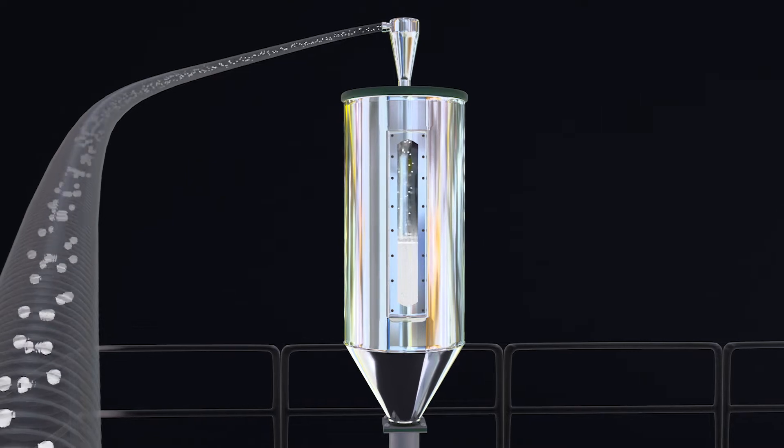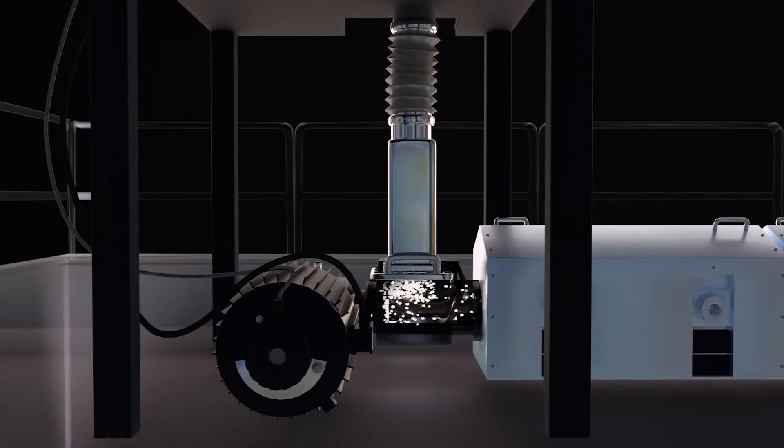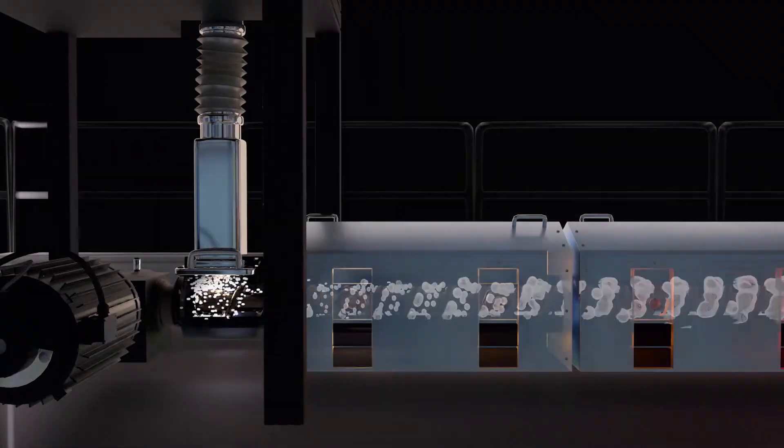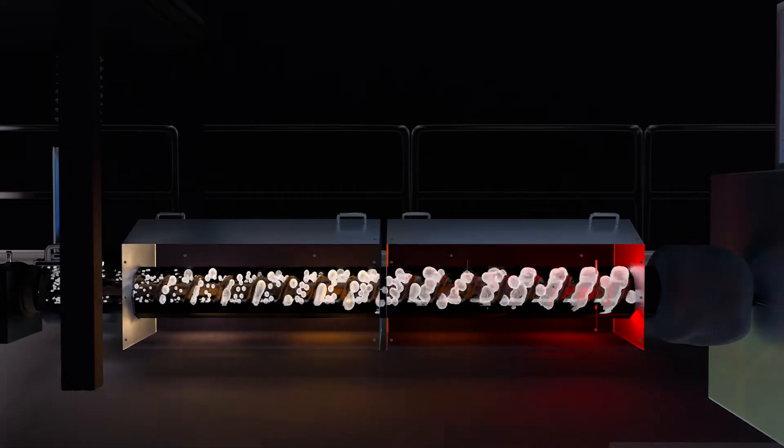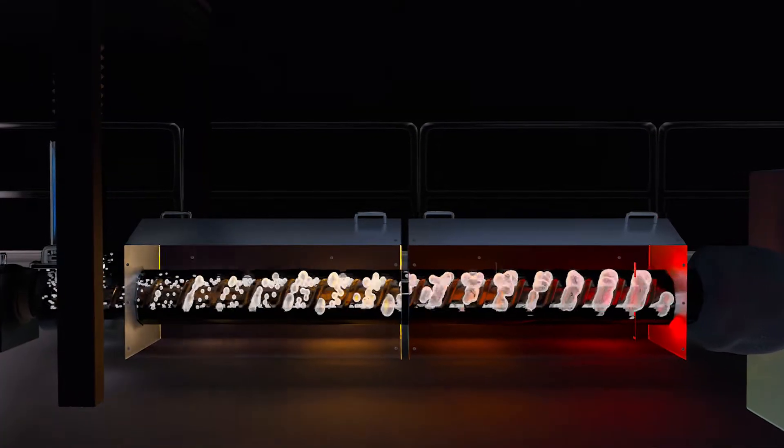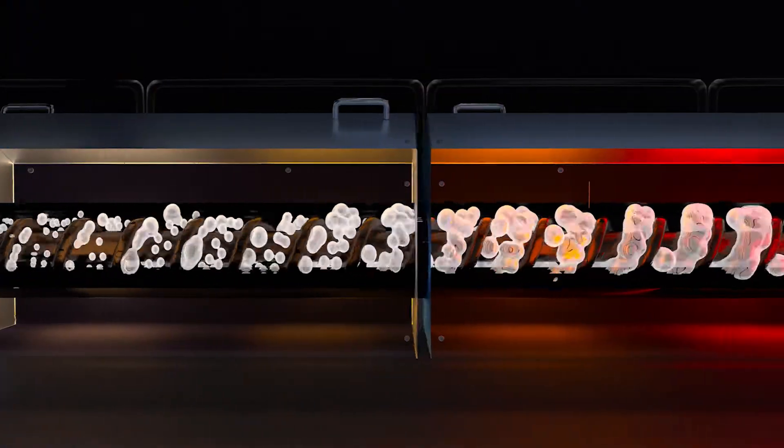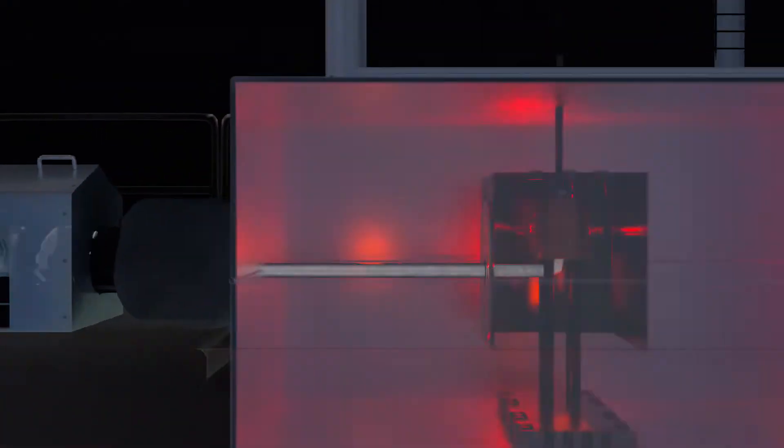Polyethylene pellets are vacuumed into a hopper, which distributes them to a large, single-screw extruder. The extruder begins pushing pellets through a melt line made up of multiple heating zones with increasing temperatures. Pellets soften as they pass through each zone and fully melt before being fed to a metering pump.